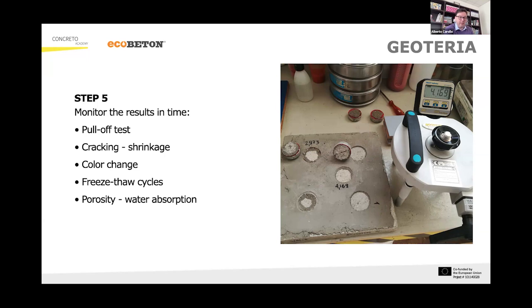And what does it mean? It means make a pull-off test. On the picture you see, what does it mean? You attach some small circles, and then with the machine you apply a force to extract them, and then you measure how strong the bond is, and you have to look at cracking, at shrinkage, at everything that happens at the interface, or even the color change, because we want to keep the color stable and matching the original color as much as possible, for example. And what happens after freeze-thaw cycles, and what happens with porosity and water absorption, for all the reasons that I told you before. Sorry if I went a little bit quickly.